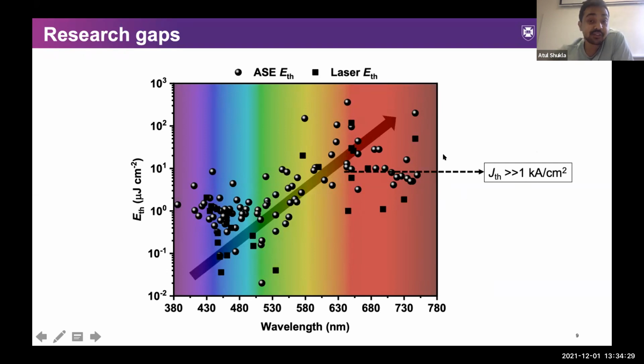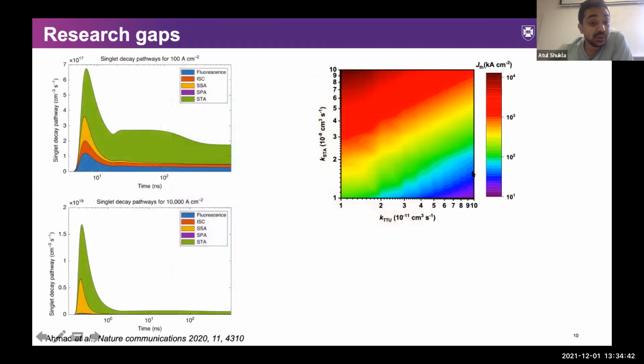And this excludes the bimolecular losses that we talked about earlier. So this is not really possible to achieve in conventional materials. And when we include the other loss pathways, we find out that STA has a major contribution in quenching the singlet excitons at high current densities. And this was shown by our group in collaboration with Bronson last year.